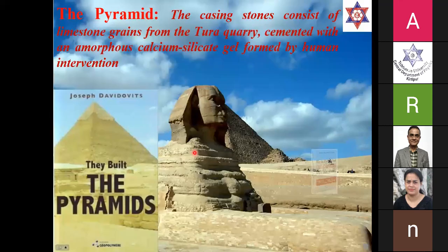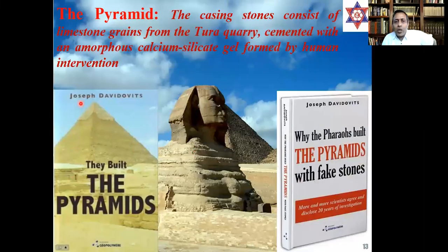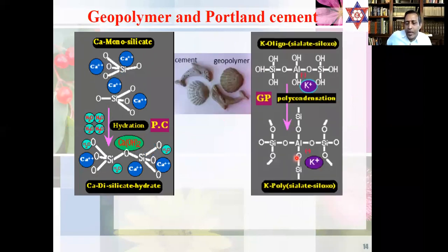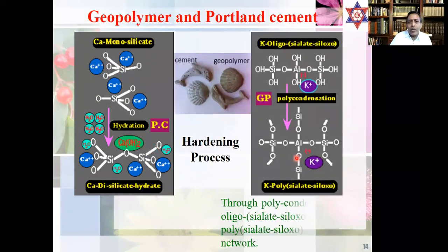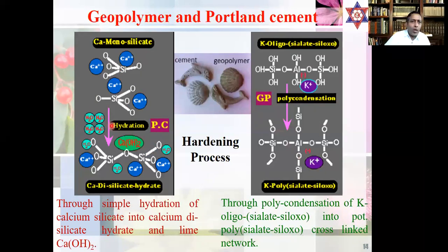These are the two books written by Professor Davidovits on geopolymer. And I just want to give you one pictorial diagram of how cement materials and geopolymers are formed. Cement material is formed through simple hydration of calcium silicate into calcium silicate hydrate, that is, what we call the CSH phase, calcium silicate hydrate phase. And geopolymeric materials are formed through polycondensation of potassium oligo-sialate-siloxo into potassium poly-sialate-siloxo cross-linked networks. This is the hardening process.